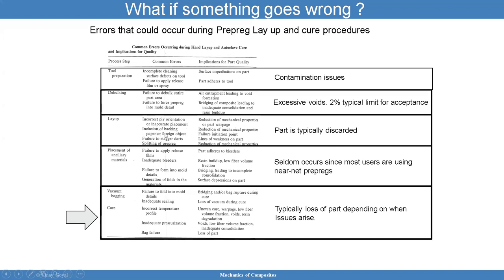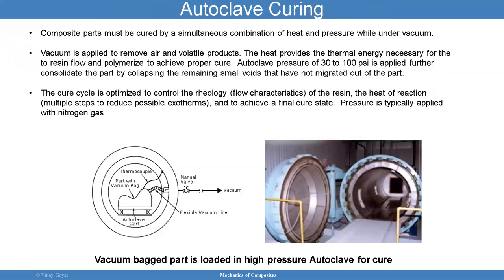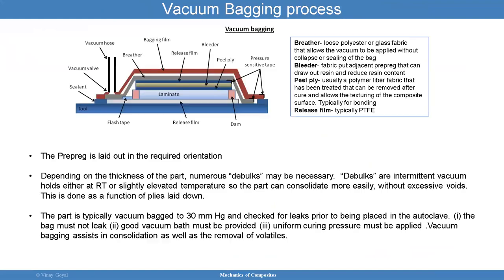Inclusion of backing paper or foreign objects. So now you have backing paper, something left behind between the plies. That's going to reduce the mechanical properties. That's not a good thing, and that will be a failure initiation point. If somebody leaves a paint chip or something between the plies, that can be a problem. And backing paper tends to be one of those things, because these rolls typically come in backing paper.